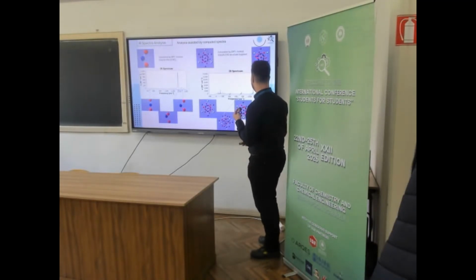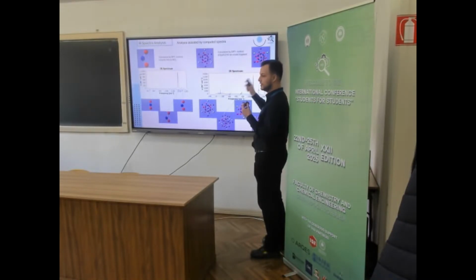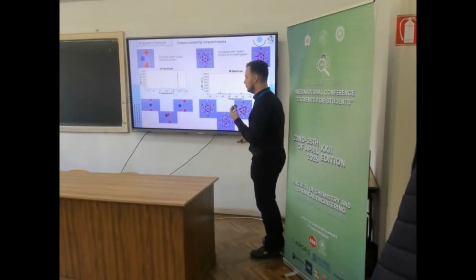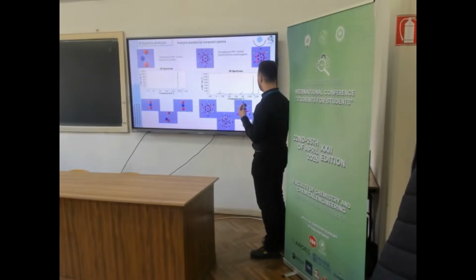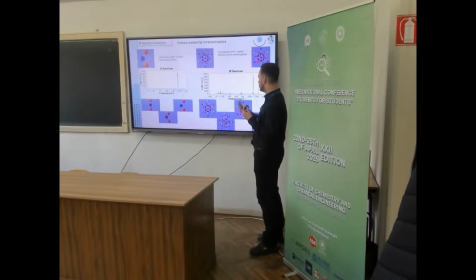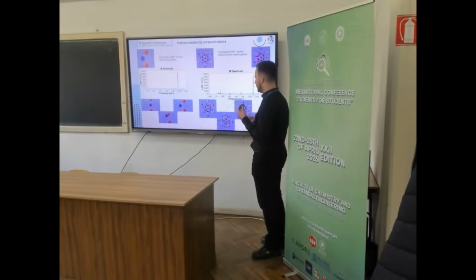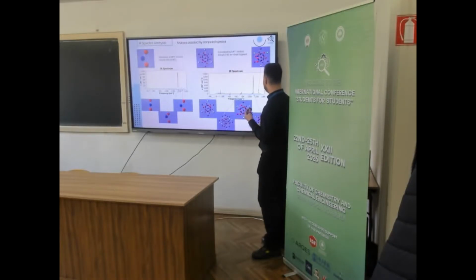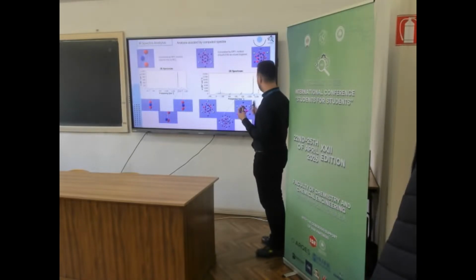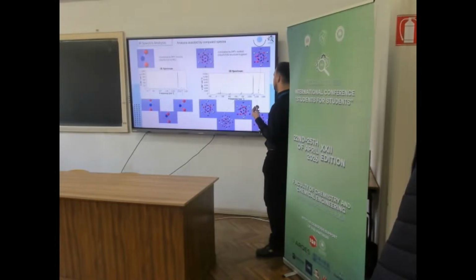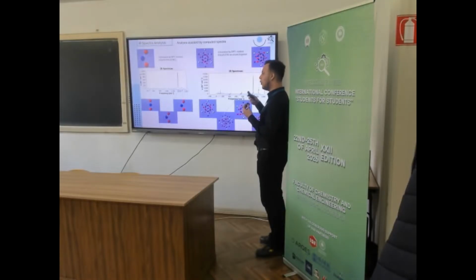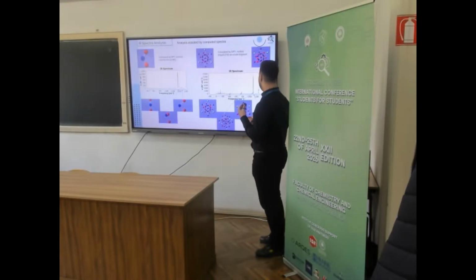And here we have the IR spectra of a chunk of the structure that I showed you with the single crystal X-ray diffraction, and the bands are in accordance. 0 to 200 are the rotational and metal-nitrogen vibrational modes. 400 is for the rocking; as you can see, it moves in the plane. This is the bending, which you can clearly see. And for these ones, they calculated two modes for the symmetrical mode and one for the asymmetrical mode. The order of the bands doesn't change, so we can safely assume that every other IR spectrum is the same. Generally speaking, we can look at the values, but not so much.